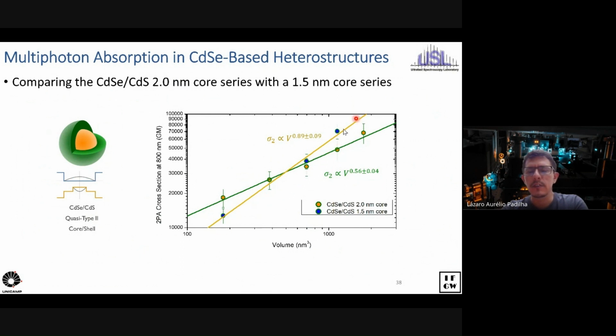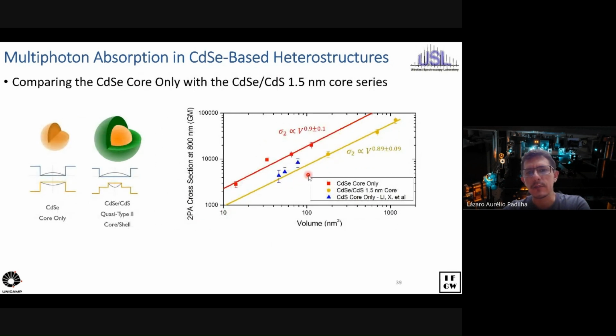And we see this interesting behavior here, where the dependence of the cross-section on the volume goes nearly to the same as what we see for core-only quantum dots. In fact, what we believe is that the core-shell here is becoming, effectively, a core only made of cadmium sulfide, pure cadmium sulfide. Here, if we compare our data for the small-core heterostructure with core-only cadmium sulfide data from the literature, we see very good agreement, suggesting that, in fact, this is the case.